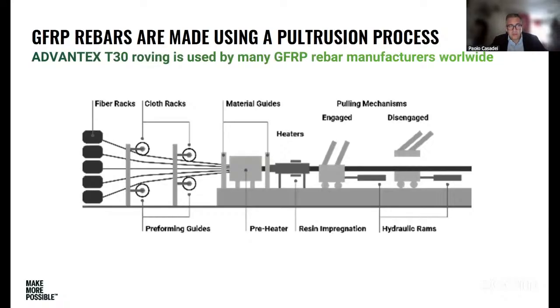How are rebars manufactured? Rebars are manufactured through a process called pultrusion, from the word pull. So it's an extrusion by which we actually pull. In reality, the process begins from the very end. The operator starts with the fibers going through a bath of resin, and then through a die, with a heater in between. In the heater and the die there is the impregnation of the fiber, and everything is tied to the very end, where hydraulic rams literally pull the fibers through the die. So the process really starts from the end and not from the beginning.